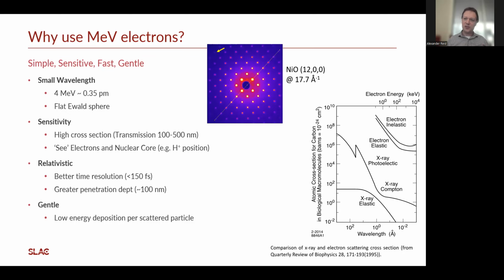Third, because we're dealing with relativistic electrons, it means that the Coulomb effects of space charge blowing up the electron bunch and smearing our time resolution are reduced. So we can maintain a short pulse over a longer propagation distance. And this allows more development of the sample environment around this. At the moment, the instrument has an overall time resolution of about 150 femtoseconds. The actual electron pulses are about 70 to 80 femtoseconds long.